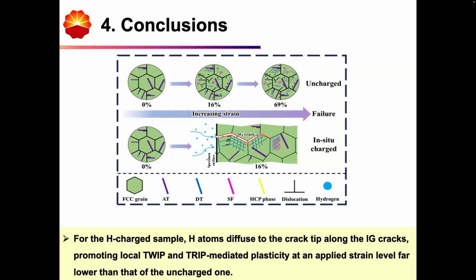Therefore it has strong interactions with the materials' microstructures, causing some complicated nanodomain structures, and the combined effects of the lamellar and also the deformation twins will promote the initiation and propagation of the intergranular cracks.